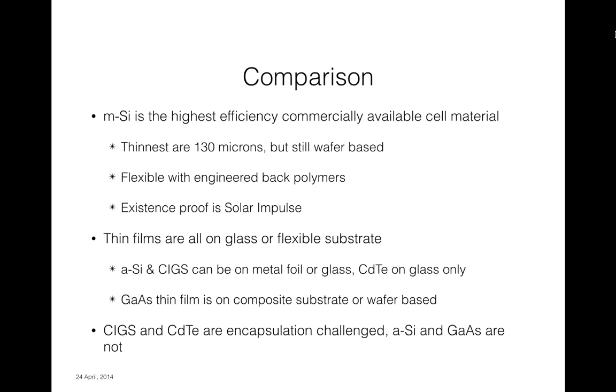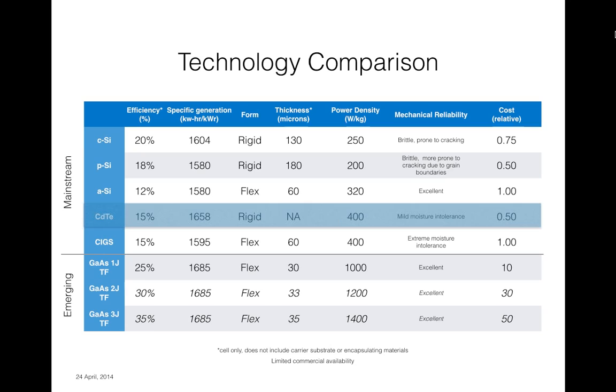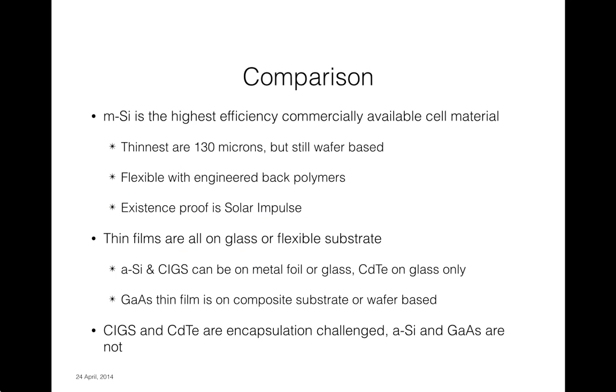Yeah, gallium arsenide is definitely what I would recommend, and I would look at it in its thin film form. The figure of merit here is the energy density, the power density. There is no other material that approaches 1,000 watts per kilogram and can do it in a really thin form. The practical challenges of trying to integrate a rigid silicon cell are really hard, and they only lend themselves to large aircraft where there are gentle bend radii. Then you can apply them.